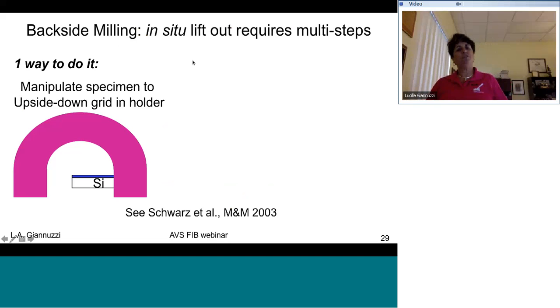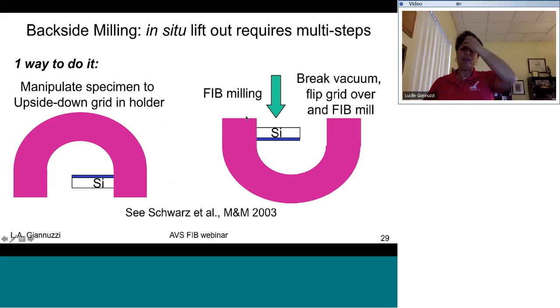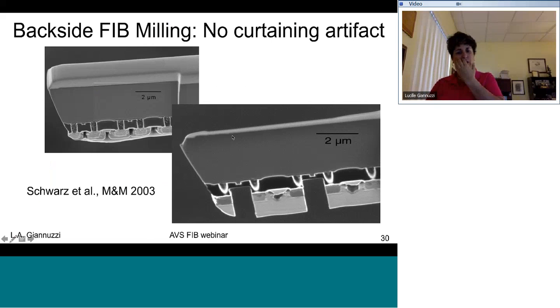Okay, another way to reduce curtaining is to FIB mill from the back side. So one way to do this, and this is something we did years ago, was to mount the grid upside down into the FIB. So when you do the lift out, then if this is your silicon substrate and you've got metal layers up here, the sample is lifted out in the same way. But then you have to attach it to the grid. But then you break vacuum, flip the grid over, and now you can FIB mill from the back side. And this was work that we did, which we subsequently gave to Martha McCartney at ASU to do some electron work on. So we FIB mill this from the back side, and you can see now that there's no curtain artifacts in the silicon.